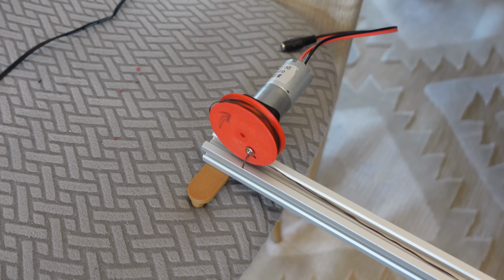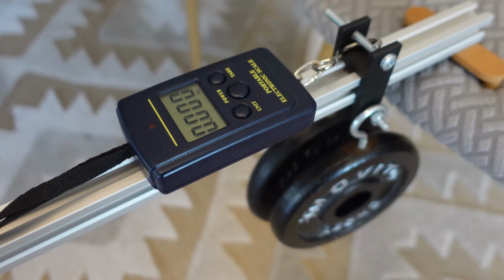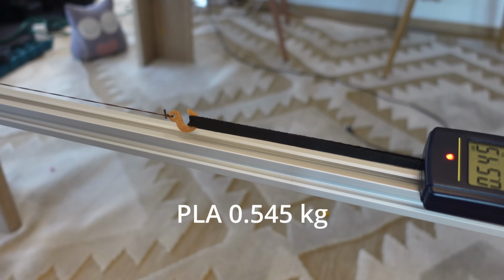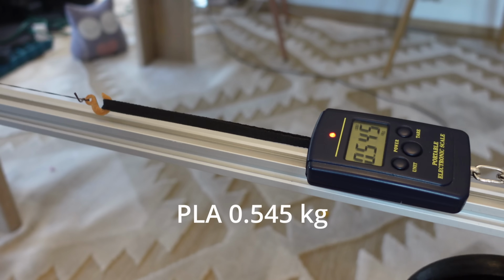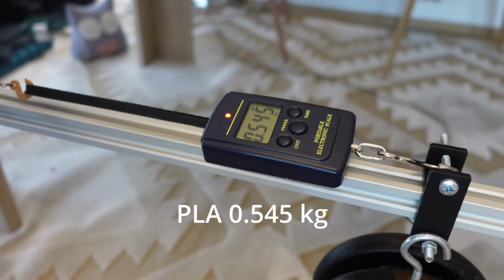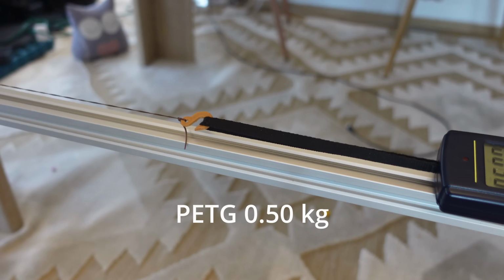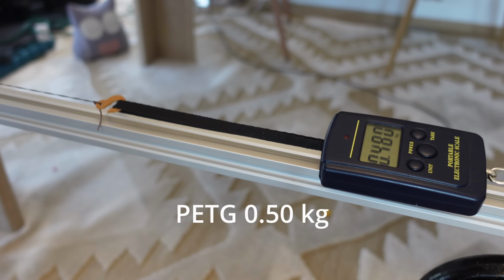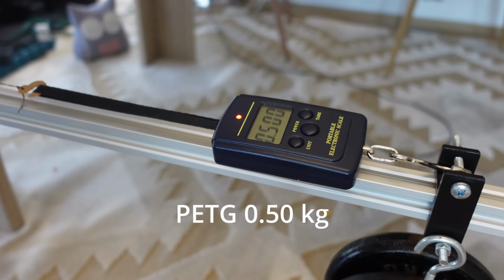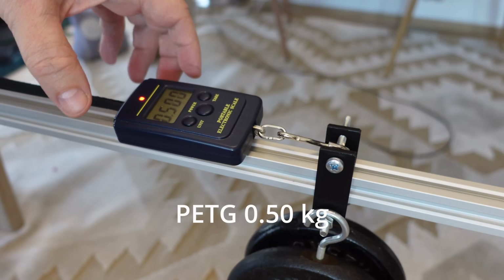And now let's measure the sliding friction. The speed is not big, only 2 meters per minute, but it is still a sliding friction. PLA: 0.54 approximately. And the PETG, 0.5 kilograms. Again less friction with the PETG.